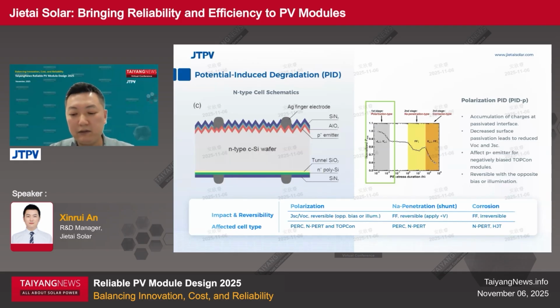For the n-type TOPCon modules, it mainly affects the front p-type emitter, P+ emitter, when the cells are under negative bias with respect to the module frame. And the kickoff voltage for PID-P can be quite low as 50 volts. So it may impact the small rooftop PV systems and also large PV stations alike. PID-P can be fully recovered by applying the opposite bias, or in the case of the aluminum oxide and silicon nitride passivated p-type surface, simply with the illumination or long-term storage for the charges to dissipate over time.